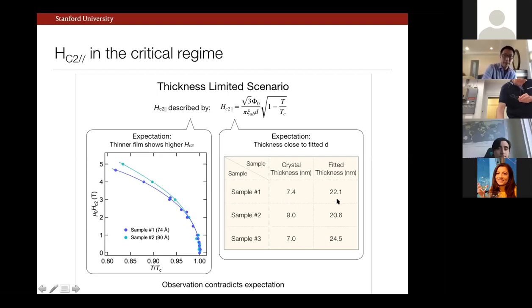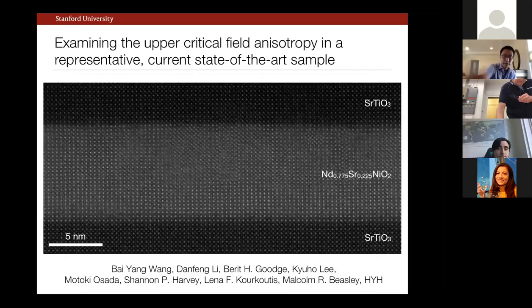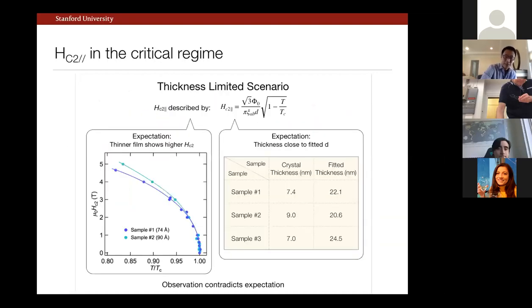And so what we see is actually, although there's a beautiful square root temperature dependence, the numbers are terribly off, not a few percent, but we're talking about factors of 3 or more in terms of the known crystal thickness that we can measure by, for example, X-ray scattering measurements, or in this case, say by just TEM, direct inspection. You can see here that the thickness we derive from this Tinkham-like fit is horribly off. And it's even going in the wrong direction. Namely, if I went from thick to thin, I would expect HC to go up. But actually, asymptotically approaching TC, they all look the same. So this is very puzzling, and it experimentally shows us that we are not actually thickness limited.